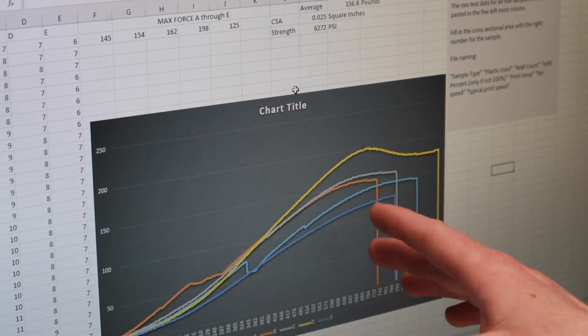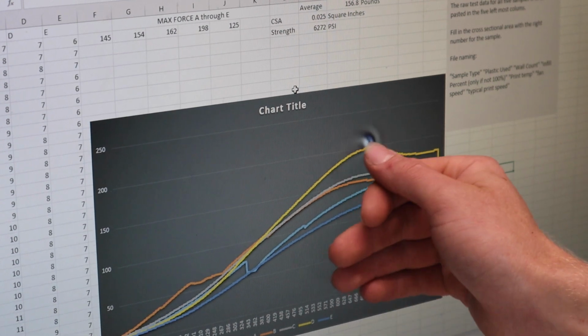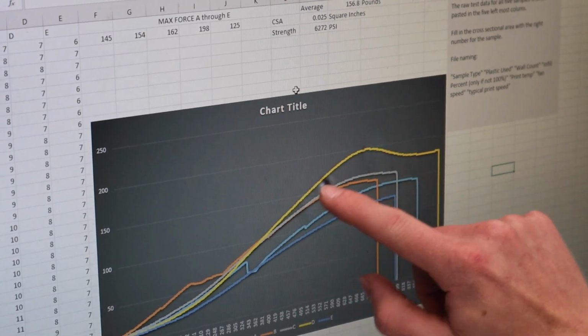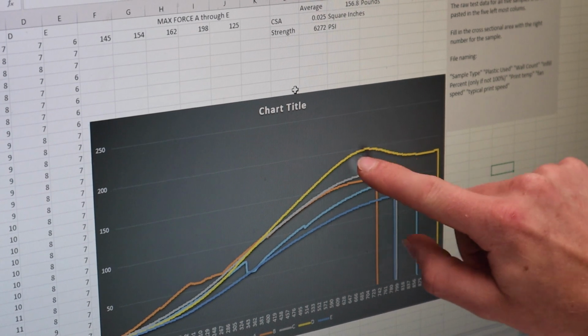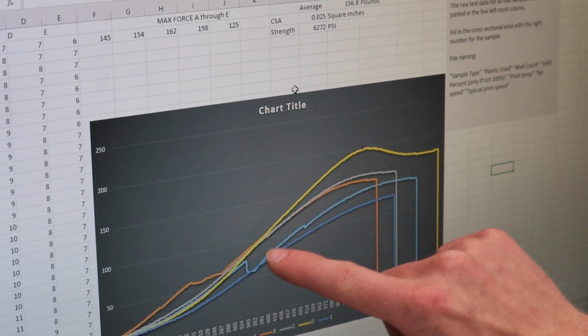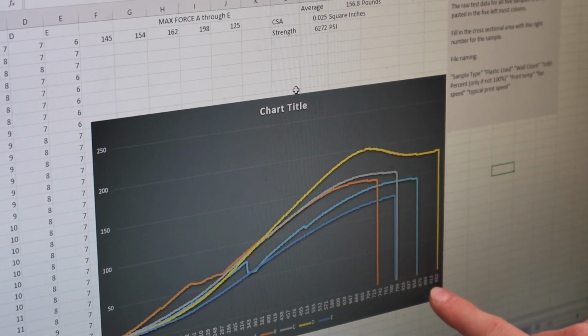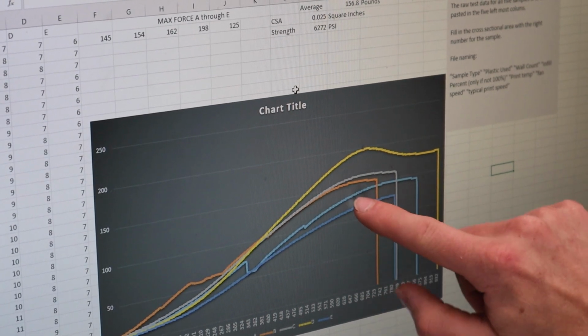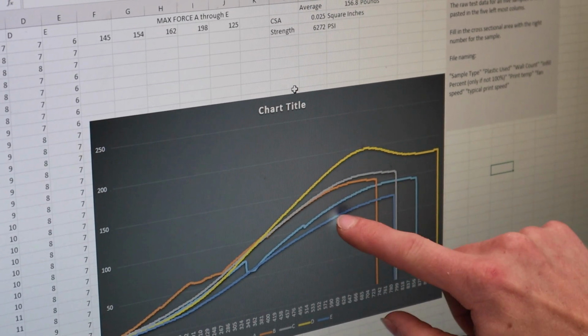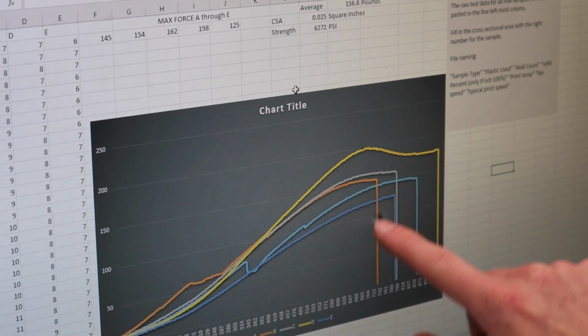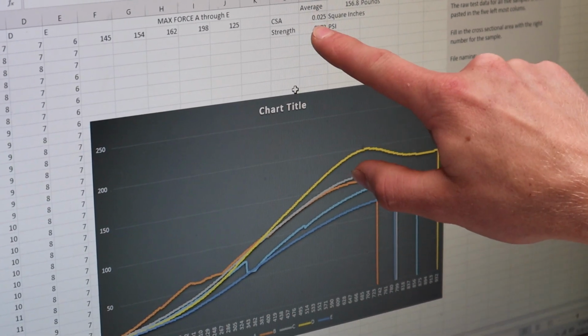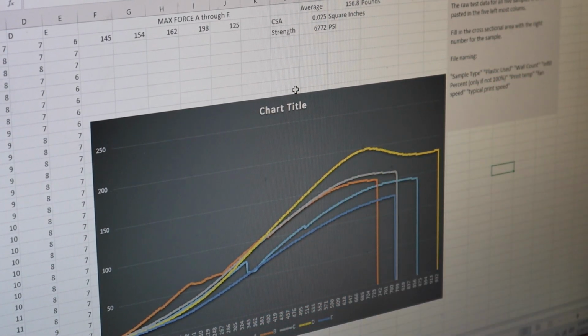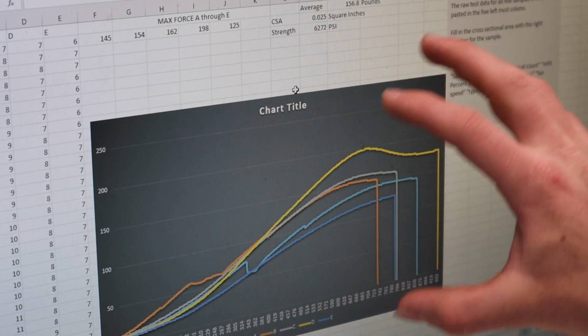Though obviously layer orientation is not that important with resin prints. Not important at all. Now looking at the chart here, you can see that the strong sample right here had a nice yield point, I should say. Ductility is the wrong word, I believe. It yielded nicely and then finally broke. All the samples did that to a more or less degree, very slightly, with the exception of number E right here, which snapped off. My guess why the strength of the horizontal test samples is less than the vertical test samples is probably because the parts were cured differently. He probably printed them at a different time and cured them differently.